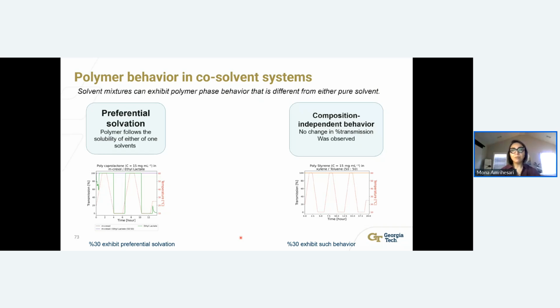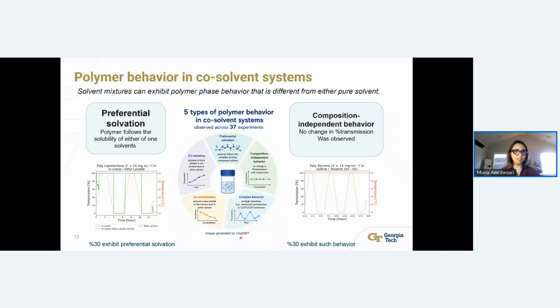But another case study that we also looked at is the composition-independent behavior. 30% of such behavior is that there is no change in transmission whatsoever. It stays at 100% or 0% throughout the experiments. So this shows at least 5 different ways that we thought it might happen, and it happened with this experimental design system. There is still more to come, but this experiment has been done as a preliminary screening to see what would happen and how the transmissivity would change based on the knowledge and parameters that we are talking about.